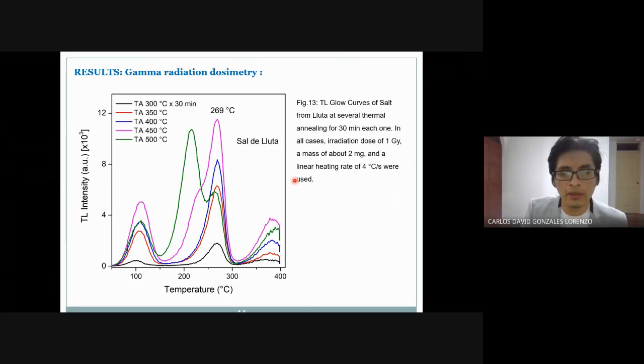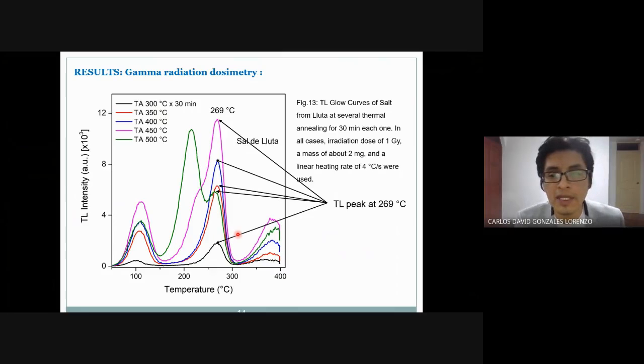In this case, we show TL glow curves of salt of Lluta at several thermal annealing temperatures for 30 minutes, increasing in steps of 50 degrees from 300 to 500 degrees Celsius. You can see here one interesting point: the TL peak at about 269 degrees Celsius. This peak is very sensitive and is also located at a high temperature, which is an advantage, for example, if we want to use this peak as a dosimetric peak.